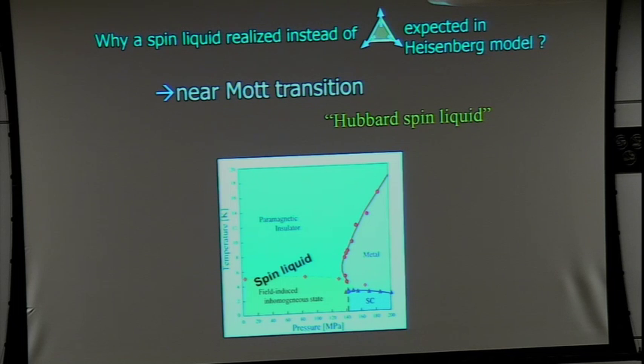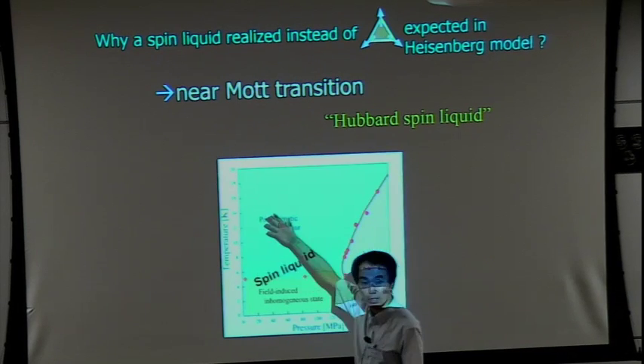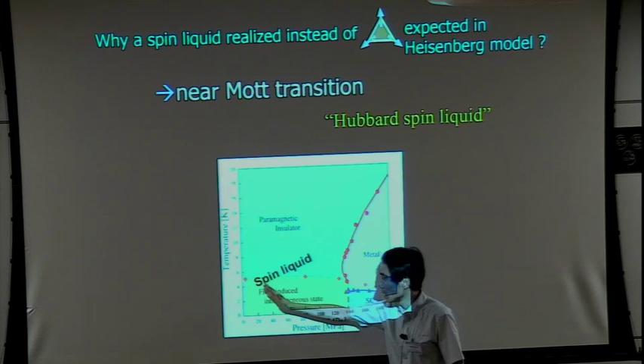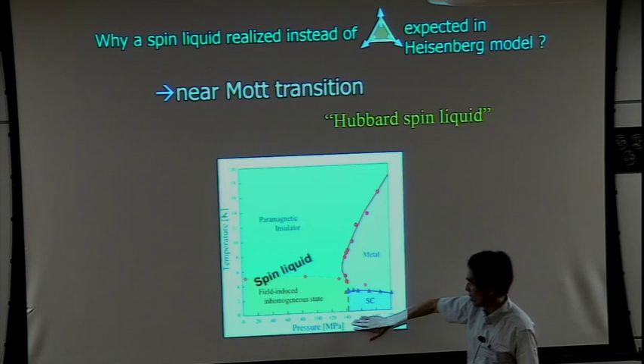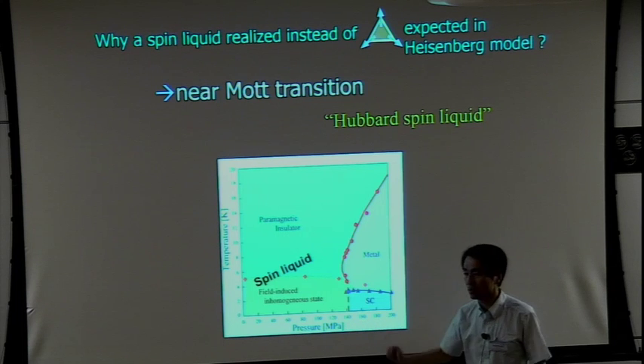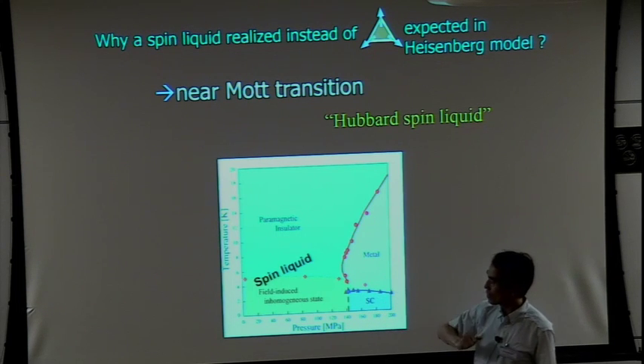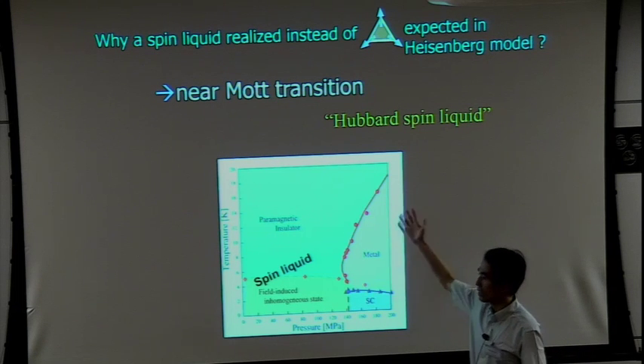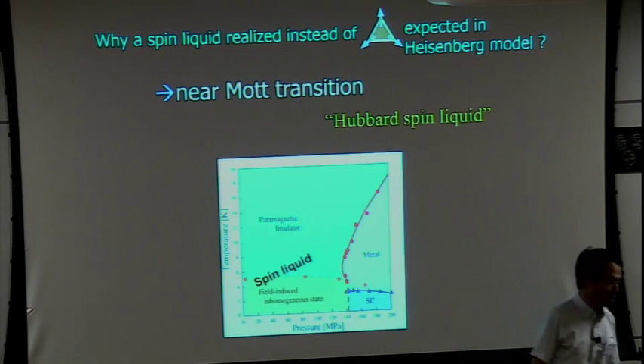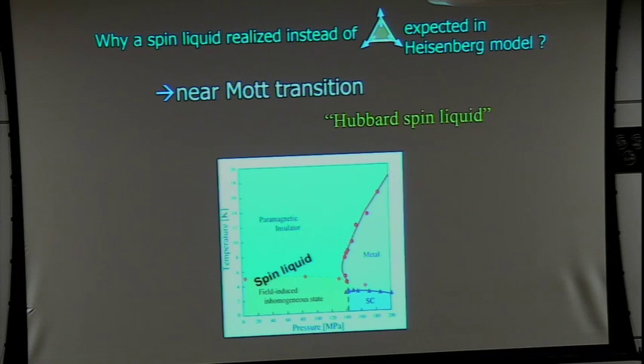This is the experimental phase diagram of a spin liquid. At ambient pressure, this system does not show spin ordering - it's a spin liquid - and under pressure it becomes metal. 140 megapascal is a relatively small pressure, so this material at ambient pressure is very close to the Mott boundary. From this phase diagram, we can say that the spin states of these materials should not be described by the Heisenberg model - maybe the Hubbard model or extended Hubbard model is more suitable.